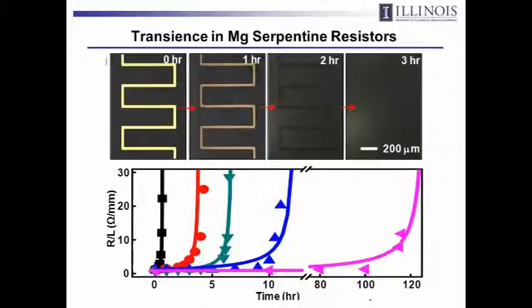Here's an example of a time sequence of images for a serpentine trace of magnesium. And as you can see, just in a few hours, magnesium will completely disappear. You can measure the resistance, and you can see that disappearance. So here it is, just in a couple of hours, the resistance will go from a very small value to a very high one. Now, if you encapsulate the thing, you add magnesium oxide on top, it dissolves at a slower rate, so you have very little change in resistance, and then once the magnesium oxide is gone, the resistance starts to increase rapidly as the magnesium is dissolved. And then likewise, you use different thicknesses of magnesium oxide.